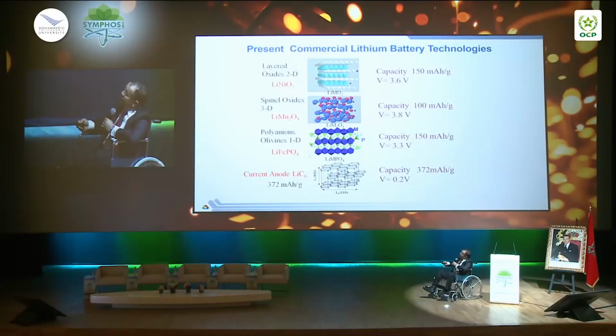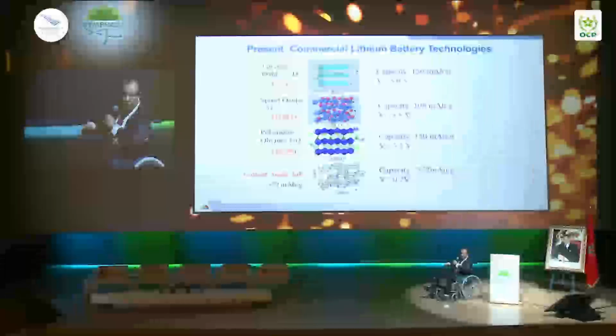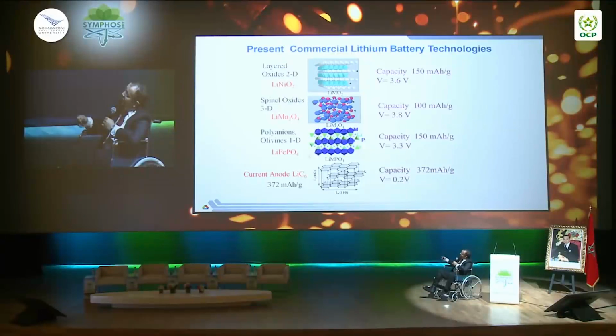So these are the major components that are commercially available now. You have the layered oxide in consumer electronics. We've seen some penetration in automotive now. You have the spinel, which was introduced by GM for the PHEV Volt because it has some safety considerations. And then you have the iron phosphate, which is mainly dominated by the Chinese in mostly electric vehicles and electric buses, which is a very big program. And as I mentioned, carbon is the material of choice for the anode in this case.